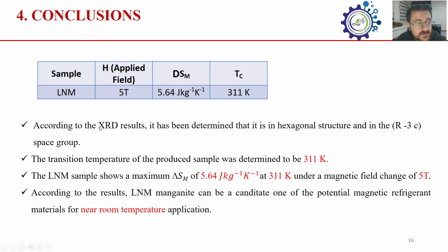According to the XRD result, it has been determined that it is a hexagonal structure. The transition temperature is 311 Kelvin, and the delta SM value is 5.64 under a magnetic field change of 5 Tesla. According to the result, LNM can be a candidate, one of the potential magnetic refrigerant materials for near room temperature applications.